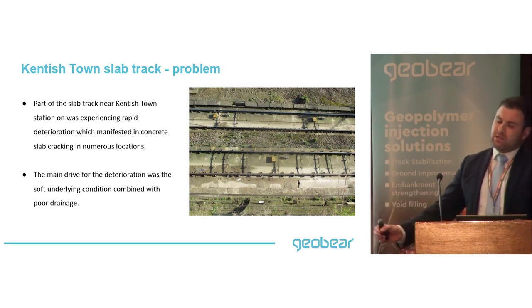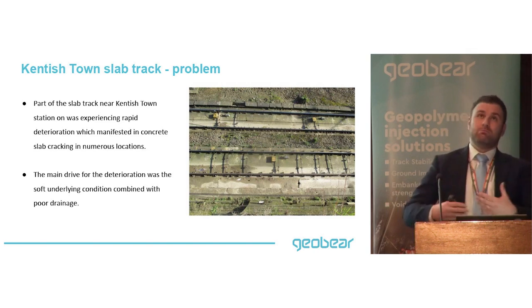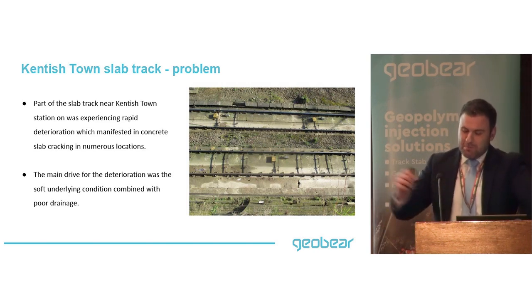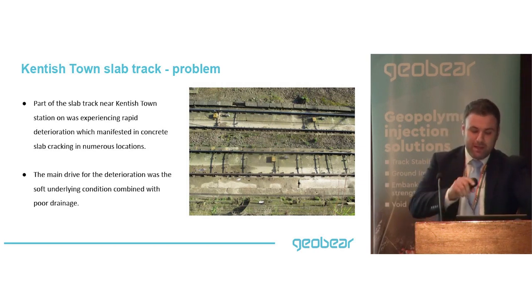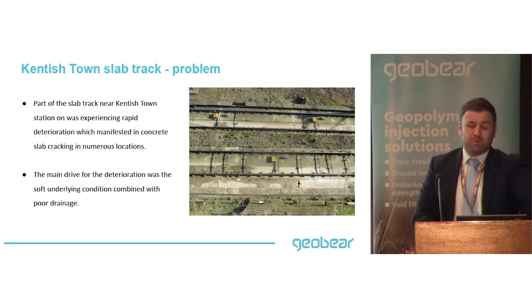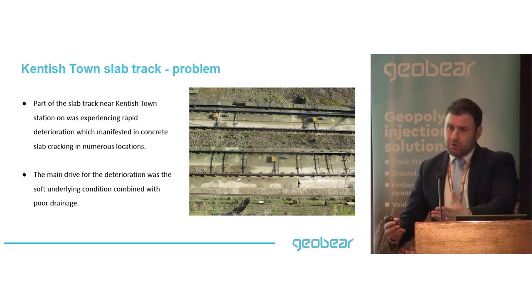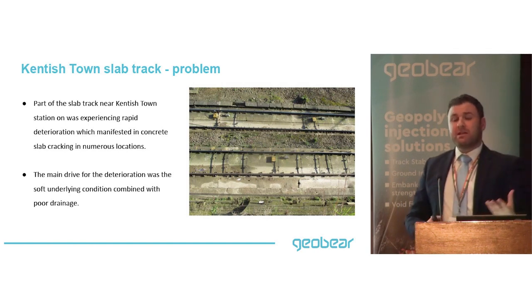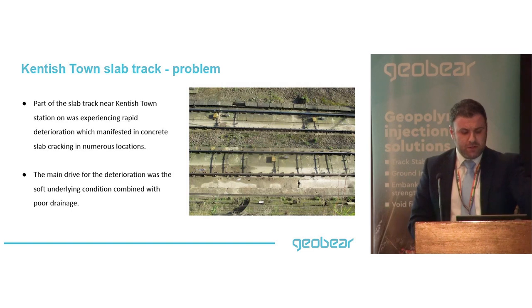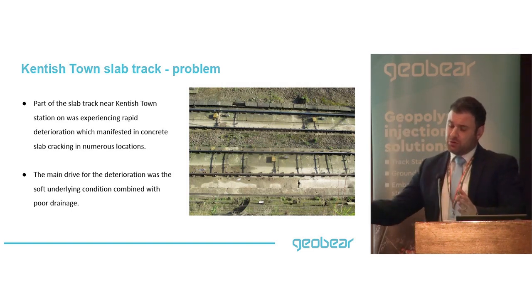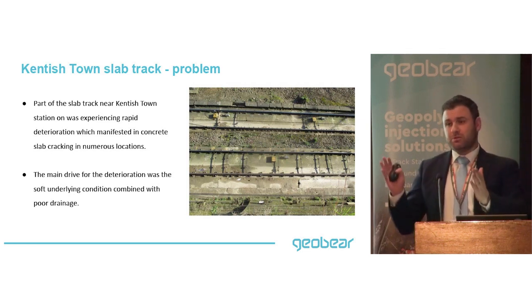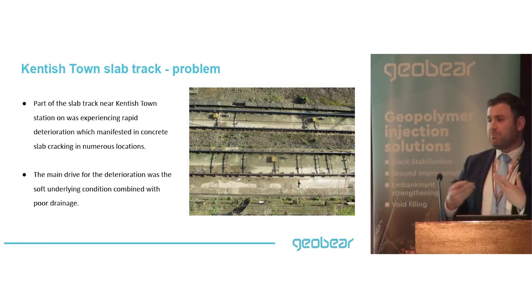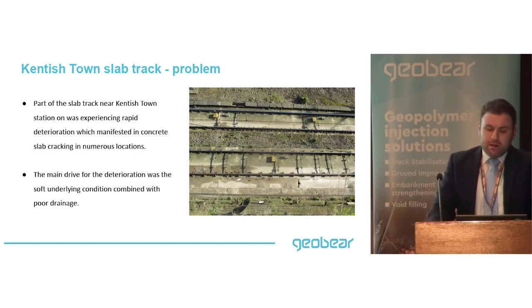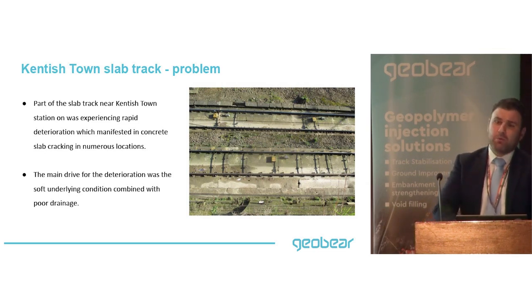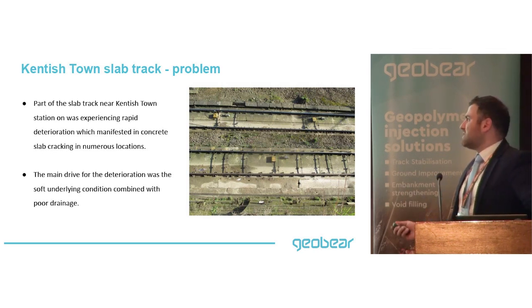Kentish Town slab track has undergone a number of renewals, with different sections having different renewals. In my previous role at Network Rail, I was involved in a certain section. This particular section was deteriorating around 2016 and was supposed to be renewed, so they planned to take out the track and replace it with ballasted track, possibly with some geosynthetics underneath. Between the time they decided to do the renewal and until they actually did it, they wanted us to come in and provide a temporary solution to stabilize the track, which was experiencing heavy deterioration and rapid degradation in track geometry due to soft underlying conditions and poor drainage.